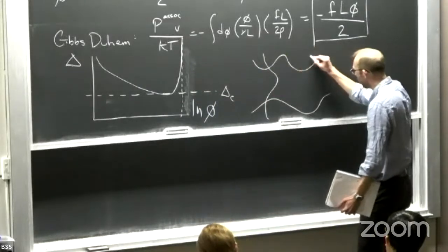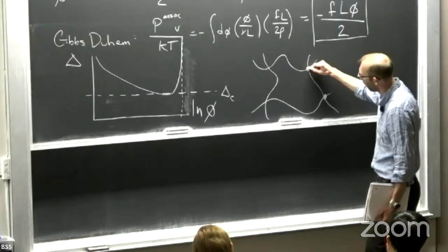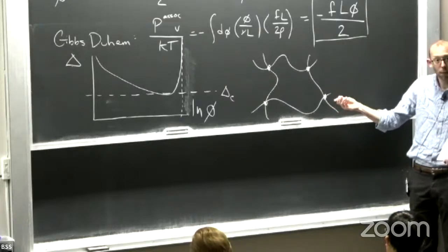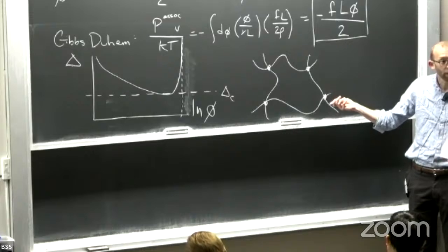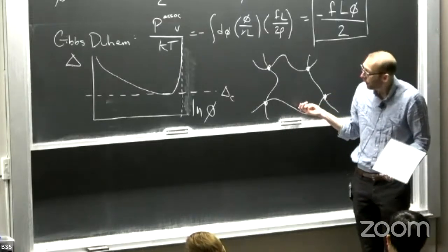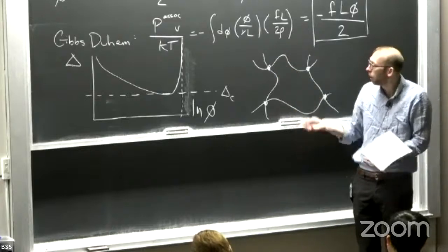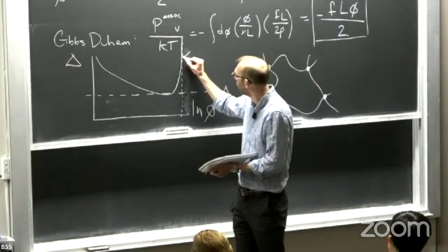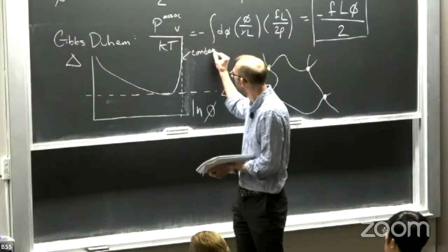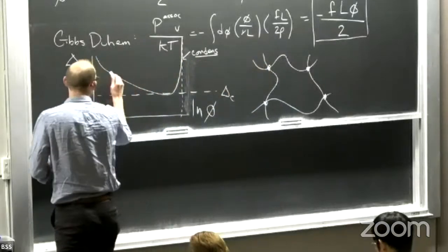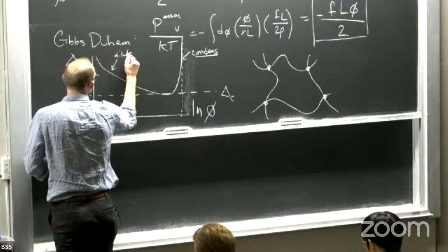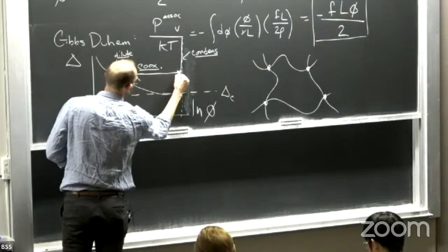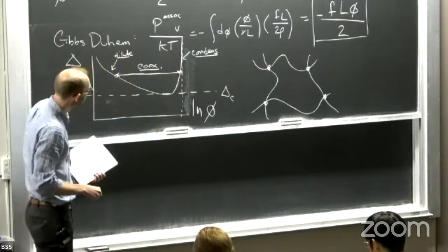Lots of open space with the polymer taking up potentially a very, very low volume fraction. And cranking up the interaction strength even more doesn't change this picture. So that's what we see here. Condensed phase. And this is our coexistence region between our two phases.